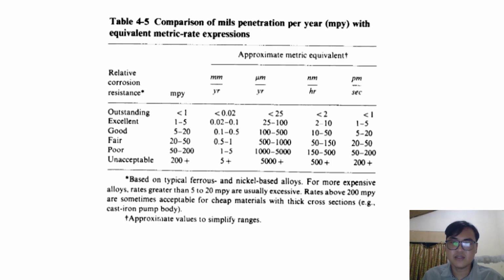This table serves as a standard industry benchmark for classifying corrosion resistance, translating raw data into qualitative performance ratings. On the far left, materials are ranked from outstanding to unacceptable. These rankings are defined by the corrosion rate, shown primarily in mils per year in the second column, with the equivalent metric units like millimeters per year provided on the right for conversion. Because stainless steel is a higher value alloy than cast iron, a rate in the fair range, which is 20 to 50 mils per year, might actually be considered too high for stainless steel.